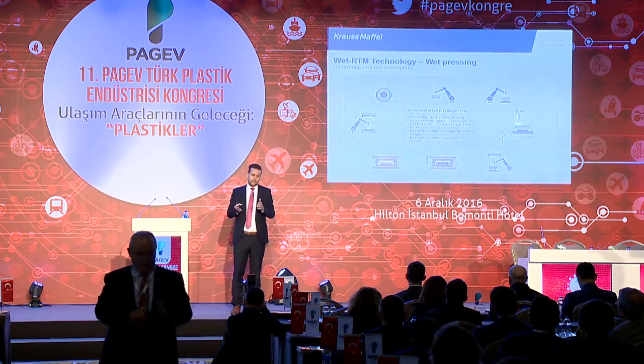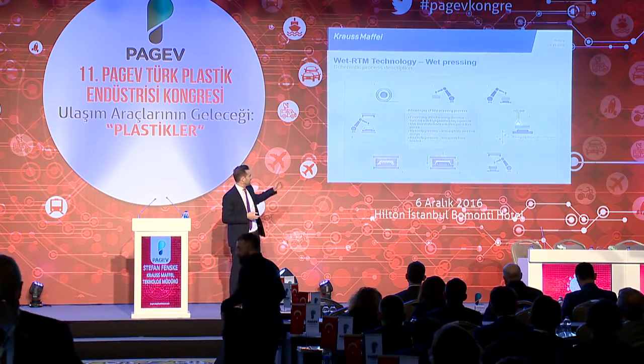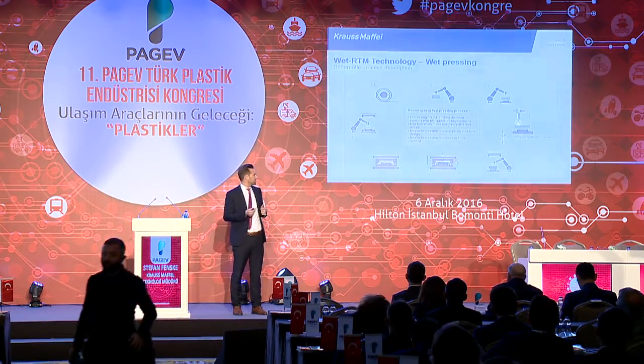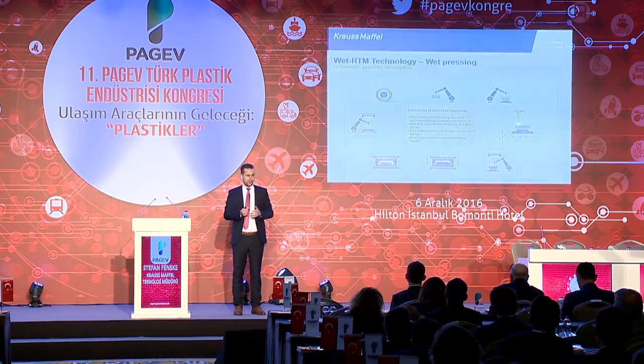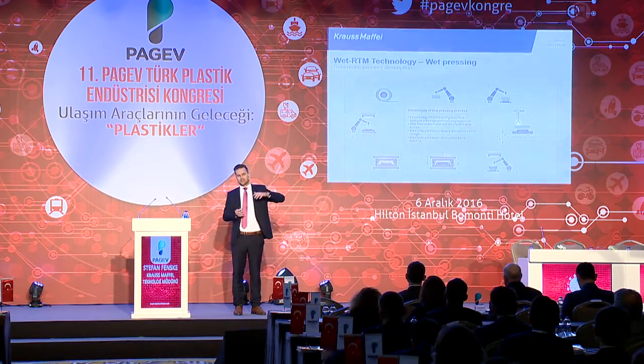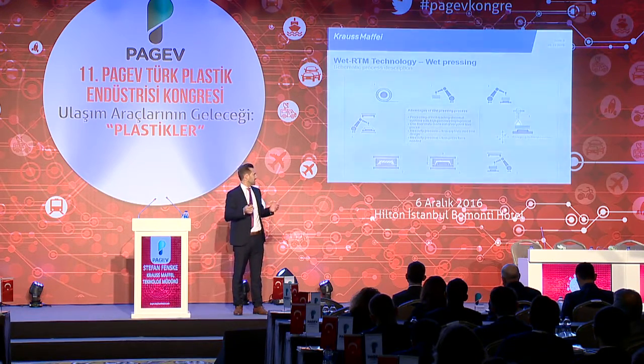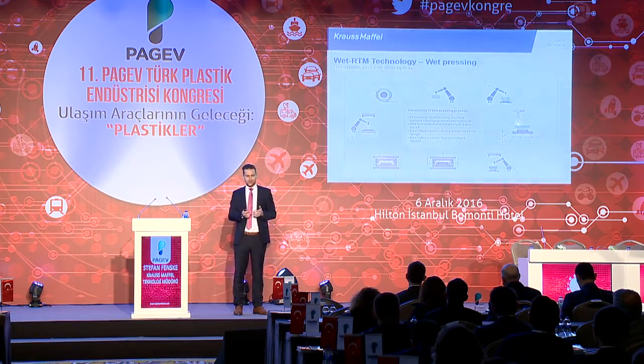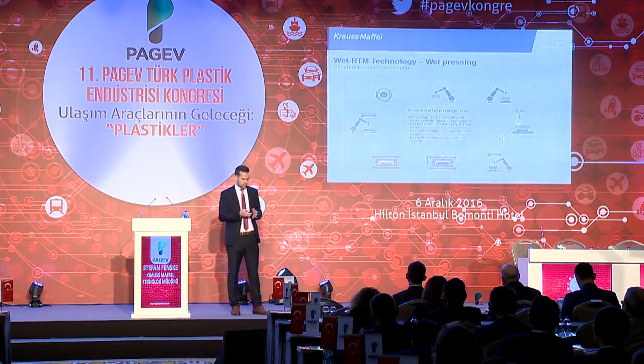What are the advantages over high-pressure resin transfer molding? Especially, you have no cavity pressure, meaning that you need less press forces. And as we, I think, all know, the tonnage of the press is the biggest cost driver in the complete process. So this is why the OEMs like BMW more or less want to substitute any high-pressure RTM process with wet pressing because the investment is much lower.